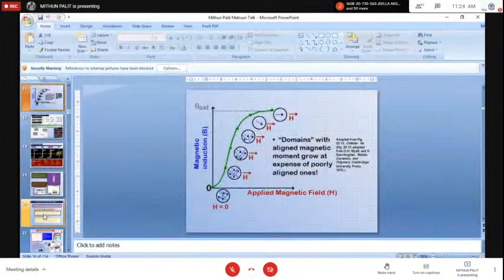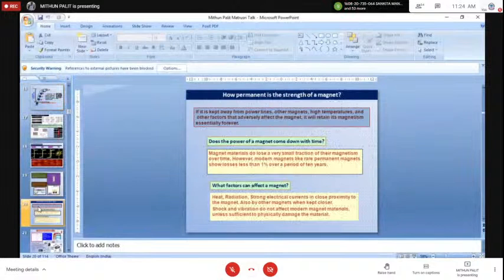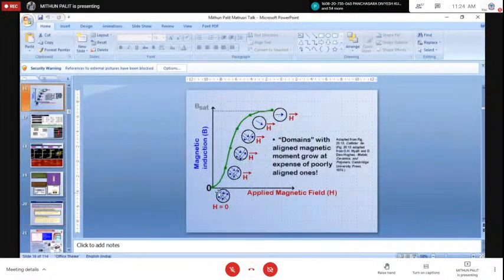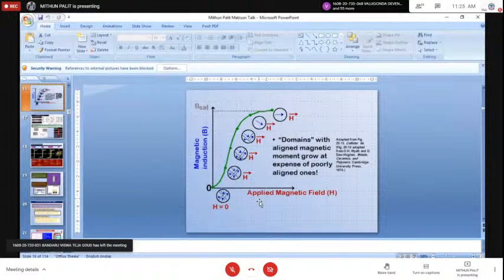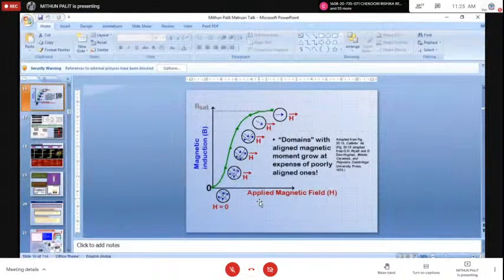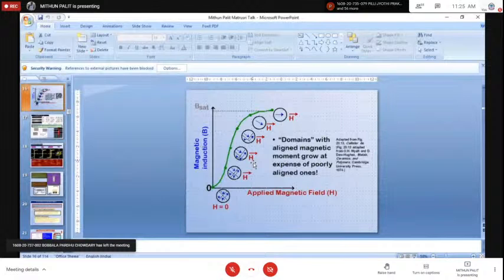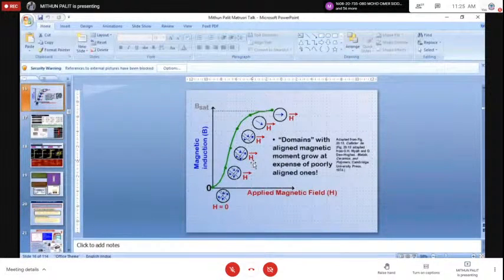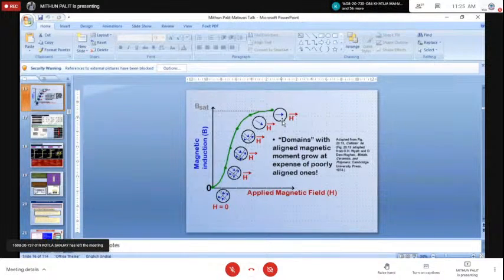This cartoon shows how the domain configuration actually changes. As I told, when we keep on increasing the magnetic field from the zero value, initially the domains which are non-favorable, which are away from the applied field direction, will first try to rotate themselves to make the entire energy condition minimized or favorable. And after that, some of the domains which have already oriented themselves along the direction of the field, being a low energy configuration, will try to grow at the cost of the other domains. And finally, at the highest field, you can see the entire material will be converted to a single direction domain, or ideally a single domain. So that is the theoretical saturation.